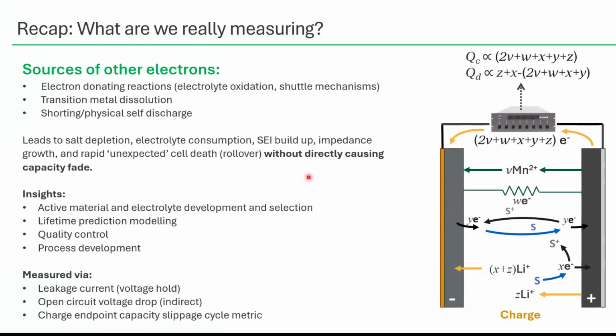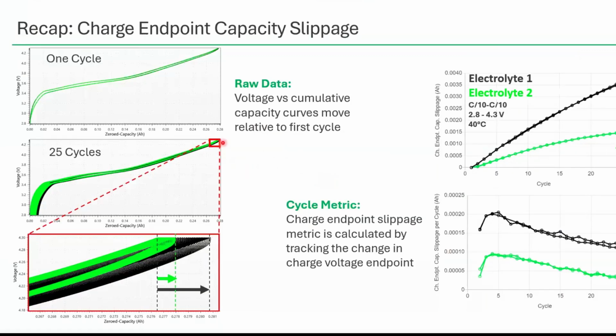During discharge, we don't come all the way back to 0. Then the next charge, we walk back a little further, and we end up with this slowly walking voltage curve out to higher and higher cumulative capacity. If we just track this endpoint, putting a pin in the map each cycle, we get this plot of charge endpoint capacity slippage.